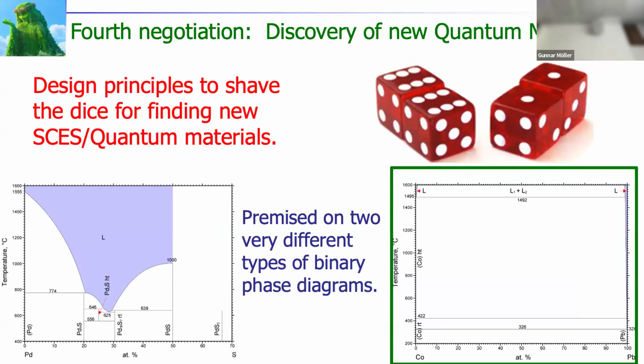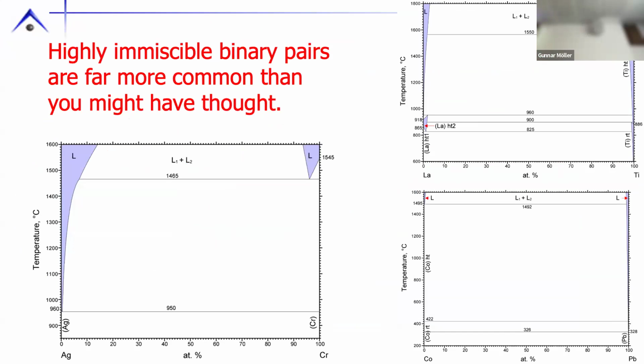All right, let me look at the other phase diagram, okay? Now remember, this is a single phase liquid. I'm not seeing a lot of single phase liquid. I've got a little bit here, I've got a little bit here, and a huge dome of immiscibility, okay? Immiscibility is oil and water. They don't want to mix, okay? And this is actually not as rare in binary phase diagrams as you may think. You have a lot of binary phase diagrams that manifest this immiscibility. And basically, these are all very similar phase diagrams. It's just a question of the temperature scale at which the top of this dome may exist.